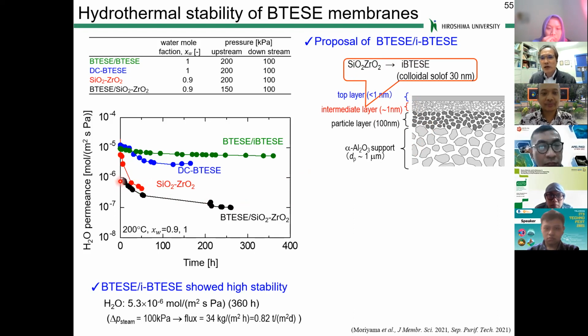So that's why the permeance decreases with time. But in the case of the iBTESE intermediate layer, BTESE, the pore size is now 1 to 2 nanometers, and the BTESE layer is, say, 5 nanometers or something. The separation layer is coated, this top layer, right? So in the case of the silica zirconia, this intermediate layer was degraded.